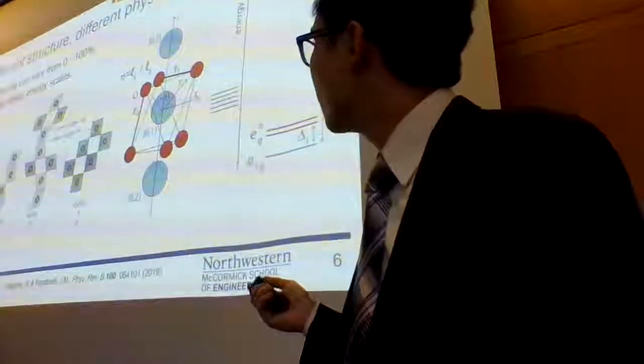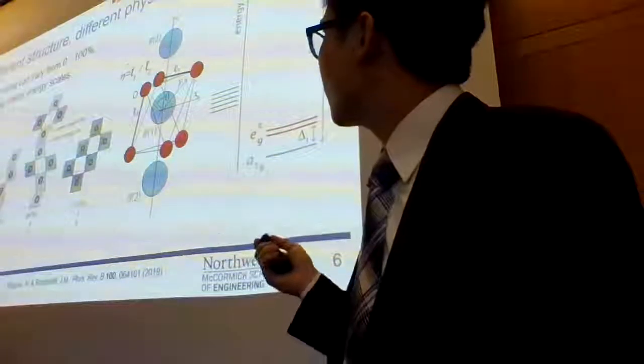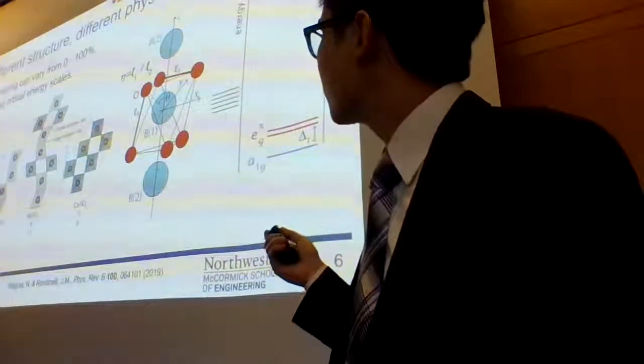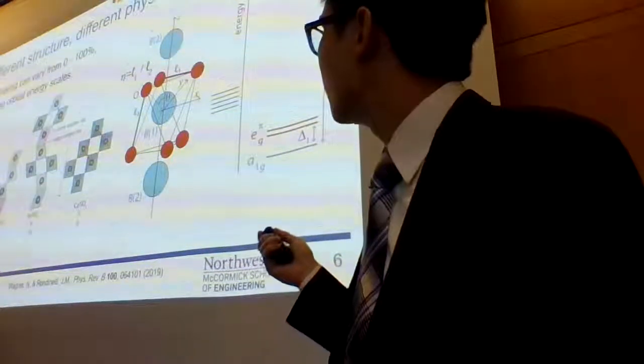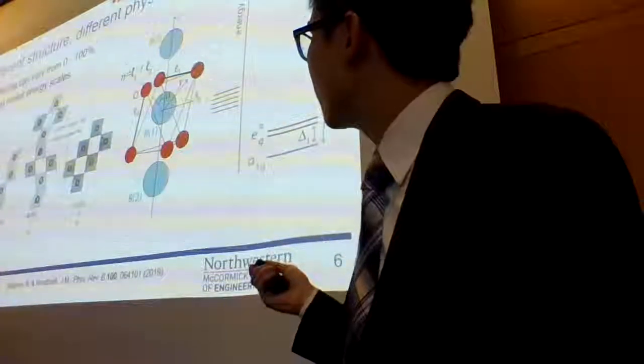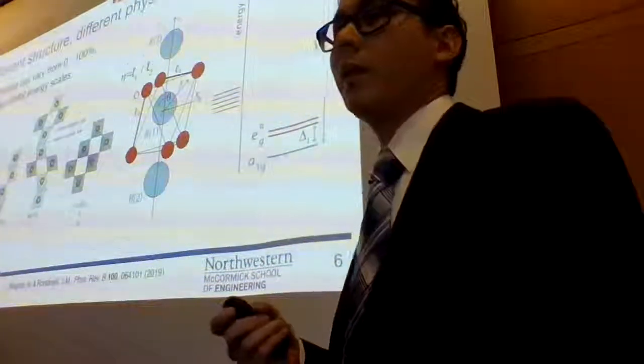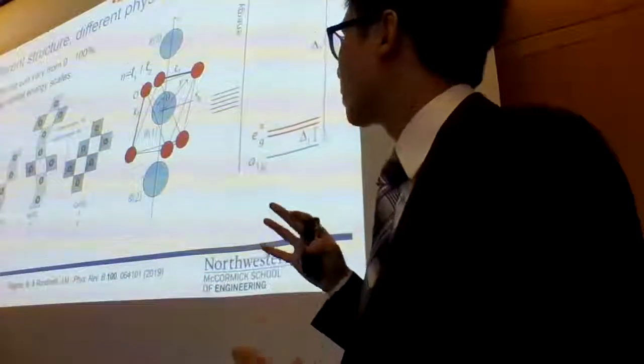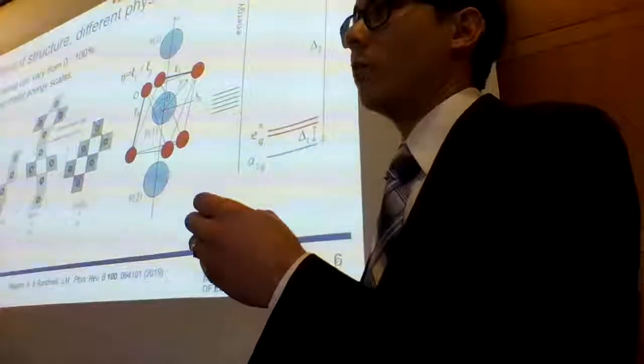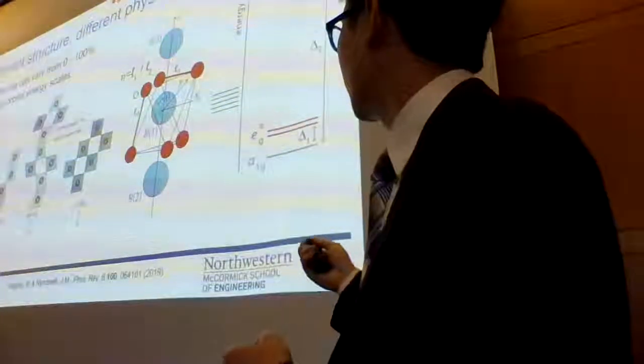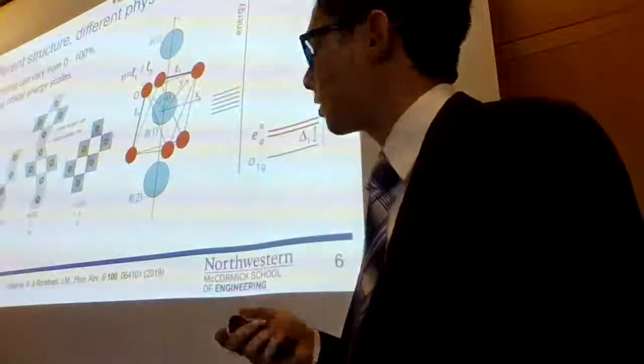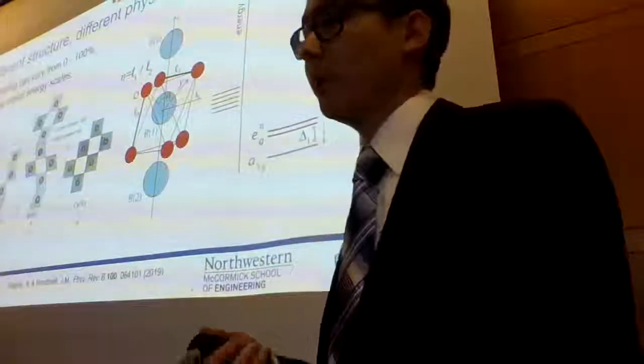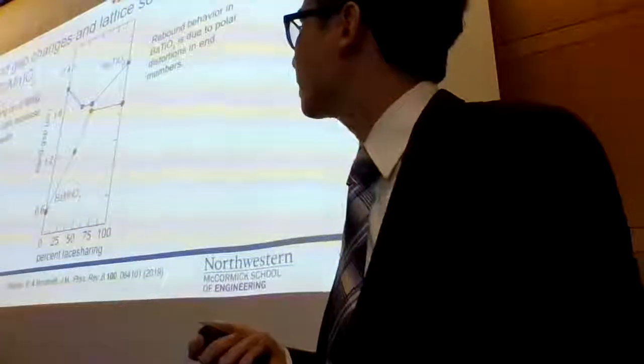One thing that I'm going to point out here, which will come up later, is this eta parameter. It's the ratio of this in-plane bond length to this out-of-plane, or along the chain, bond length. And that's going to come up later as a metric of how much of this distortion that leads to the splitting of these orbitals is in the structure. And I'll show how that's a relevant parameter for engineering properties.